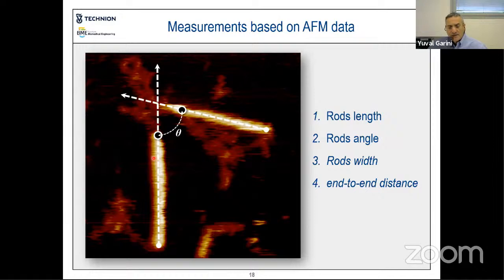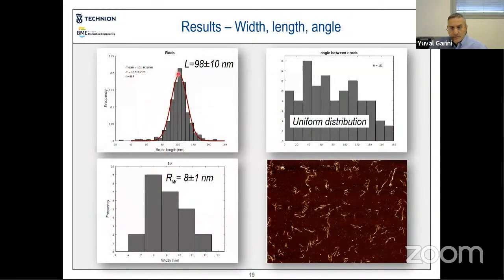If there is any, it means that something is wrong in the random process of how the structure adheres to the surface. And then we measured the end-to-end distance. We also measured the width. So you can see, for example, the distribution of the rods. It is really very close to 100 nanometer as we predicted. The width of the rod is about 8 nanometer, also what we predicted. You can see the distribution of the angles that I showed before, very close to a uniform distribution, almost with no specific angle, which shows that the distribution is really random, which is good.